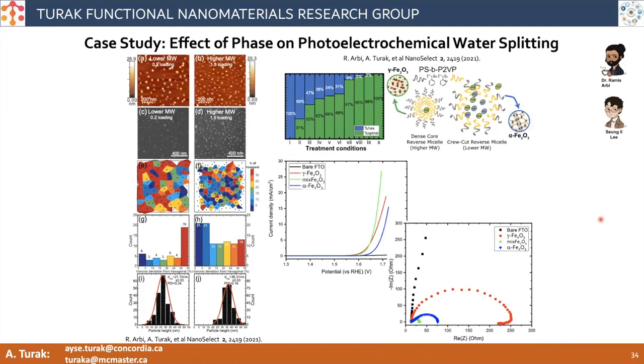And then you can couple that with looking at the phase. I skipped over this part, but one of the things that we were also able to do is tune the structure of our iron oxide nanoparticles, for example, from being purely magnetic to anti-ferromagnetic with the same size of particle.